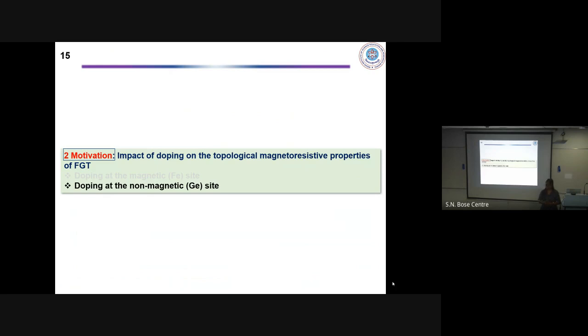Yes, it has been observed. How do you know that? From the EDAX mapping. From energy mapping, it has been shown. How can you tell from energy mapping? Yeah, the energy mapping from the high resolution TEM, they have shown that. Directly, high resolution TEM, the scanning mode. Yes. It has been, but theoretically it was said like that.